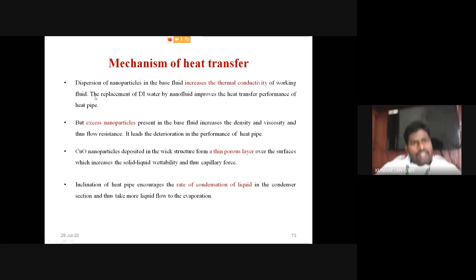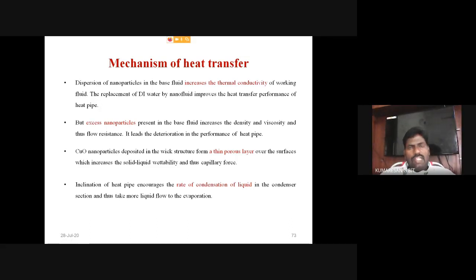The first important point is the dispersion of nanoparticles in the base fluid, which increases the thermal conductivity of the working fluid. Increased thermal conductivity of the working fluid leads to an increase in the effective thermal conductivity of the heat pipe. But if you suspend nanoparticles above 1 weight percentage, the excess amount of nanoparticles present in the base fluid increases the density and the viscosity value, and it creates resistance to the fluid flow. Then it automatically leads to deterioration in the performance of the heat pipe.